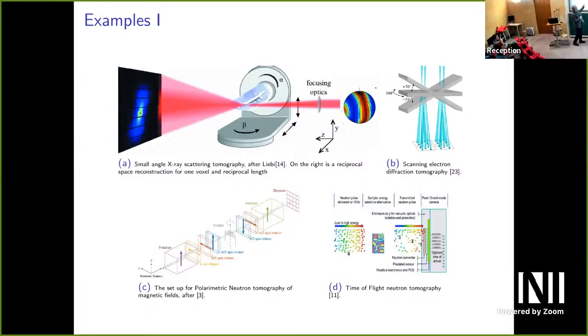So you have the beam coming in, it hits the sample, and the sample is typically on a two-axis rotate and also translate stage. So for each projection, for each of the directions, it can scan in the Cartesian directions. And then a camera measures the diffraction pattern. Typically, you don't measure the straight through ray because it's way too bright, so you blank that off.